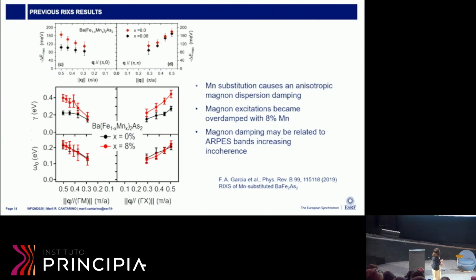But then my supervisor had already started investigating these materials just before I started my PhD, and he had this paper—RIXS results on the manganese sample—and the main result of this paper was that the manganese substitution was causing an anisotropic magnon dispersion damping. This is shown here.